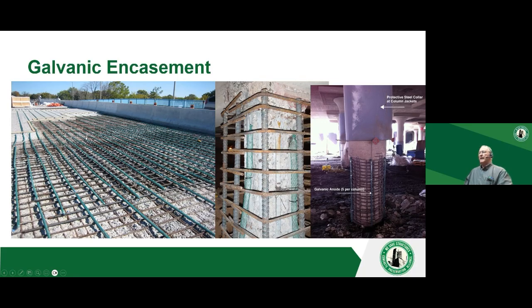Galvanic systems, galvanic encasement. This is a bridge deck. It's very similar. I've seen it in parking garages where they do a very similar application. What you're doing here is putting the anodes near the top surface once you've milled it, and you're going to protect that top layer of steel from the chlorides that are left over. A lot of times you're going to use hydrodemo.